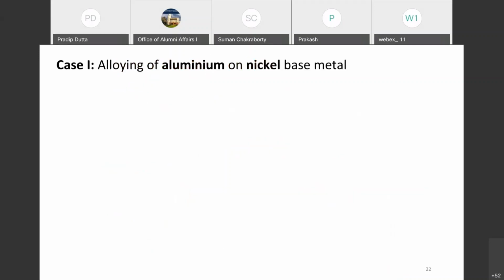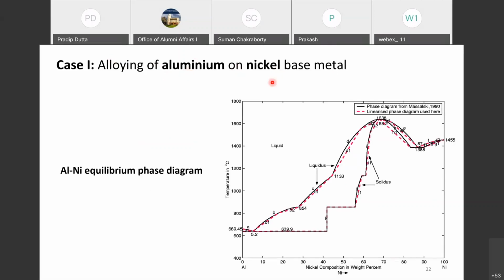Now we do two case studies. One is when we have aluminum and nickel, aluminum as a powder and nickel as the base metal. In that case, if we look at the aluminum nickel phase diagram, in the case of pure aluminum, the melting is around 600 plus degrees. And when it is pure nickel, the melting is 1455 degrees. Okay. And this is the phase diagram that we have.